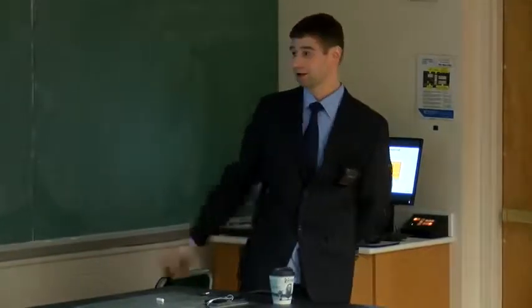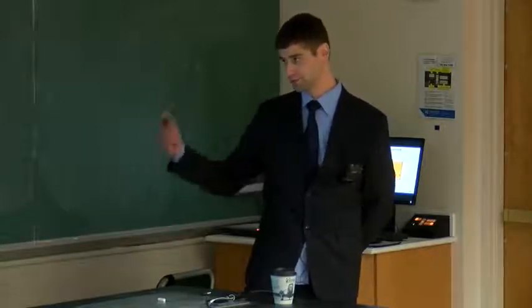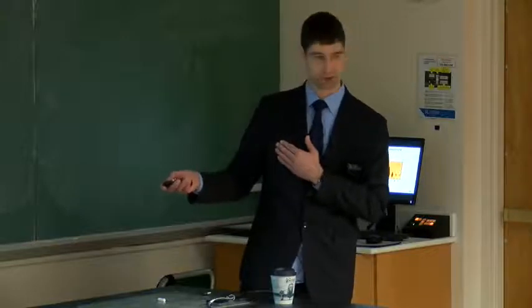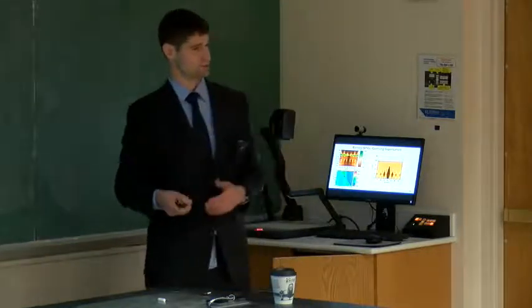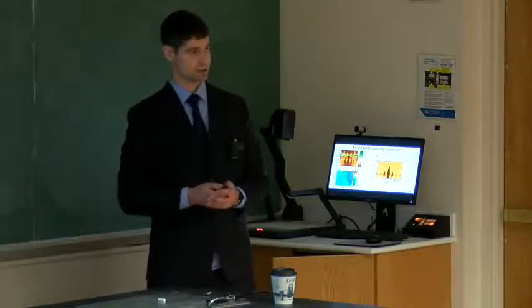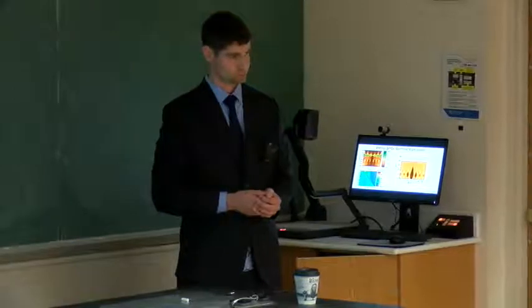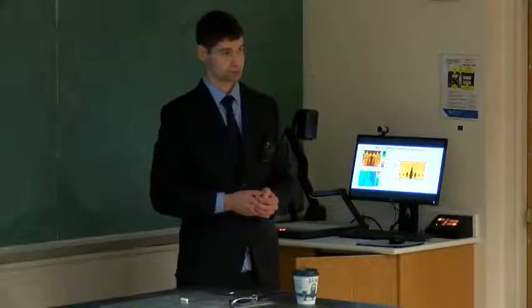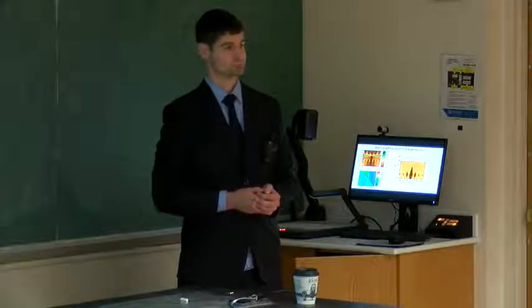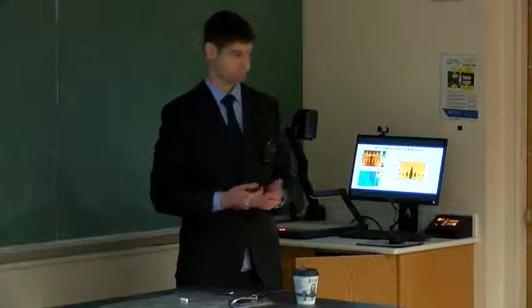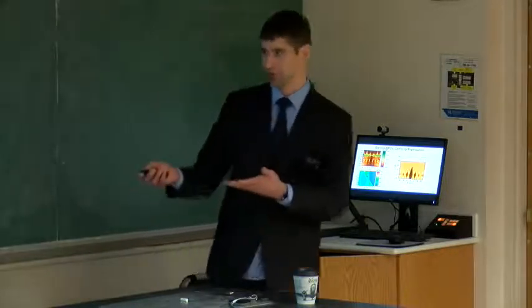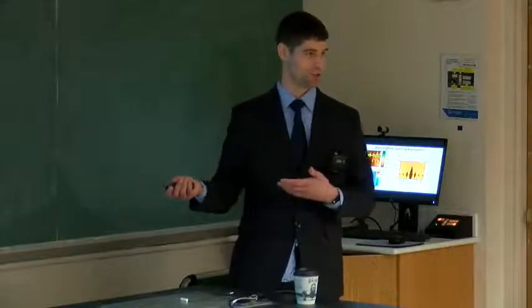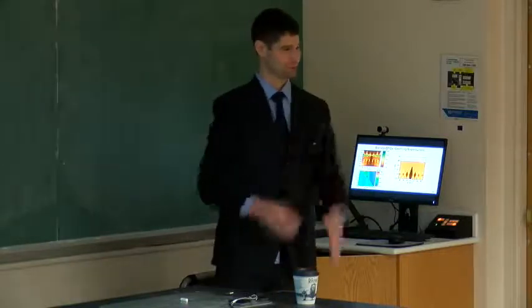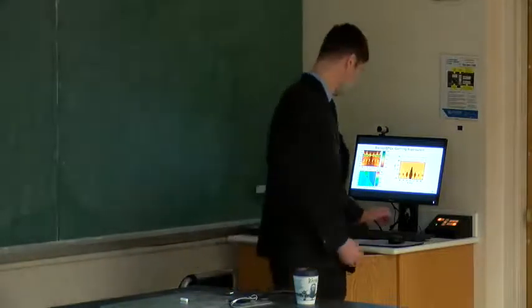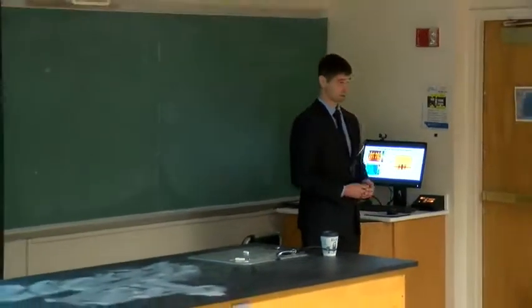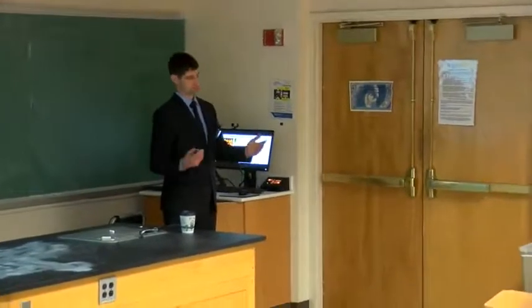You know where it is. From these, we can model it. You can take an inverse Fourier transform of the envelope of this function, and it'll give you a spatial picture, roughly, but you have to know something about the system for that. Okay, so you have a theory about where the current flows. That theory tells you this B dependence, and you successfully see the bumps in the B dependence, which then tells you where the current is. In this system, I had hoped to see some type of supercurrent quantization, but as it turns out, the electrons just flow through it. So there wasn't a lot of wonderful physics. Okay, so the current's getting spread out more and concentrated more, which is why the Fourier transform wiggles a bit. Exactly.